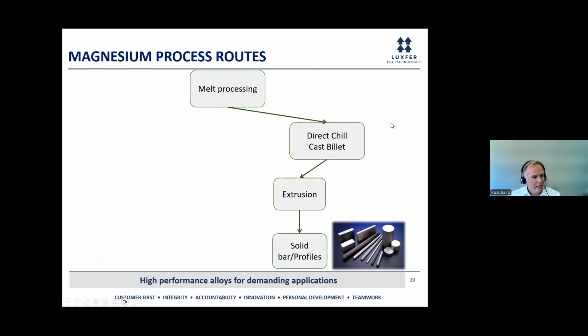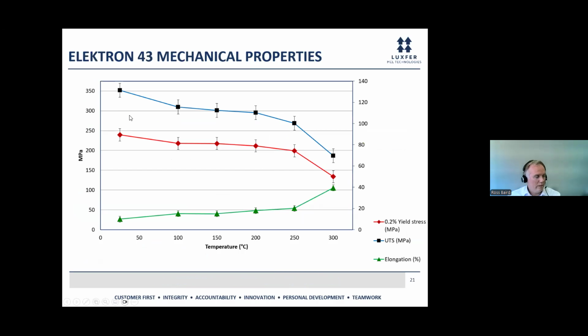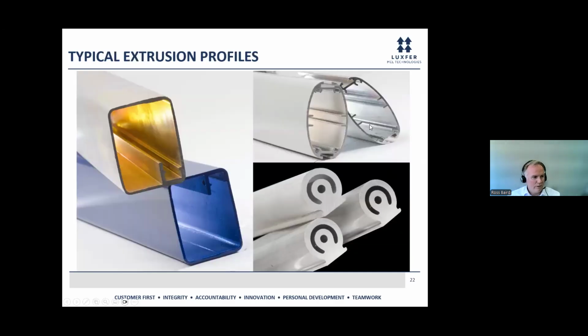I'll now move on to discussing the extrusion route, which is another alternative option. It provides slightly higher properties, ranging good properties up to 250 degrees Celsius. And this provides the option for people to specify in higher temperature areas or where they're needing higher strength requirements. You also have the opportunity now to extrude near-net shapes and some detailed profiles if required. Magnesium is harder to extrude than some other alloys such as aluminium. It takes a longer process, but it is possible to achieve and extrude components. And then from there, we take those and machine them into the final finished shapes that the customers require.